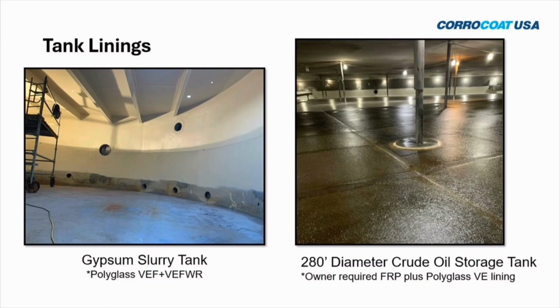Generally, when you're doing a tank lining, you work top down. It's essentially two projects. You have to build scaffolding, you have to have access to the roof and the floor. You suck all the grit out, and then you go in and do the floor. And you either maintain the overcoating window at the interface, or you resolve to sweep blast onto that so that you get a good bond in between the top and the bottom section.